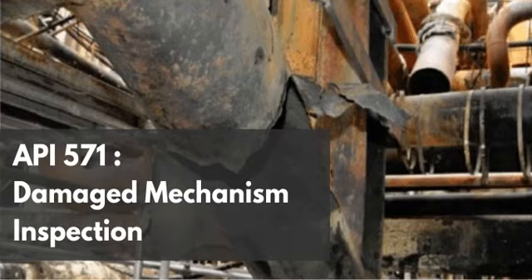But the guidelines immediately follow that strict temperature mandate with a massive, very realistic caveat regarding field execution. It explicitly states that highly restrained welds made in the field may still retain substantial residual stress even after PWHT is properly applied. And this is where metallurgical theory violently collides with field reality.